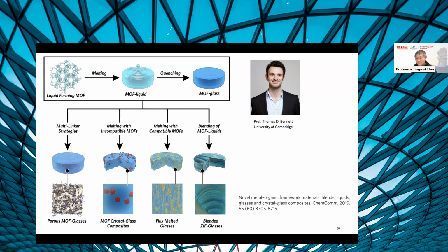But the good news is the MOF liquid is highly viscous. That means even though thermodynamically it's not stable, kinetically we can still do quick melting and quick quenching. We can still preserve the encapsulant. So if you want to know how we can monitor the degradation, there are a few techniques. If you're trying to put a crystal into the MOF glass, we can use in situ XRD to study the structure, which is very well understood. The other typical method which we use very often is DSC TGA combined with MS, because if anything decomposes, there must be something out of the flue gas, out of the TGA MS. We can keep on track.